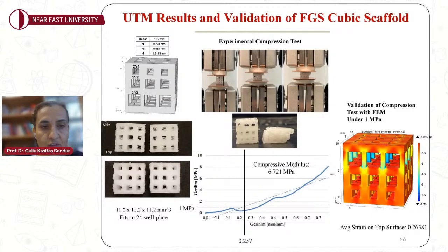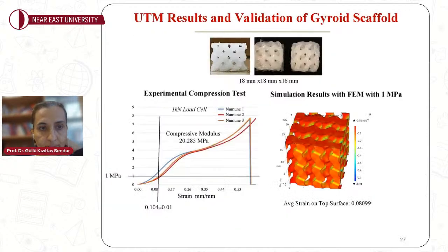UTM mechanical tests carried out this time on a functionally gradient scaffold delivered almost a one-to-one validation of the simulations with the compressive modulus and the maximum strain performance under 1 megapascal of pressure. A similar trend was observed for the gyroid structure that we fabricated using PCL in our lab, and the compressive modulus was very close to what we predicted, with a reasonable discrepancy in the strain response that we predicted using our simulation codes.